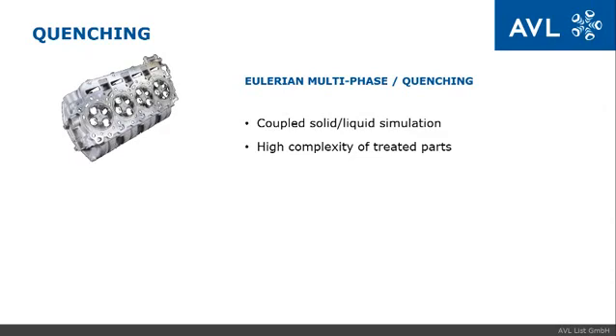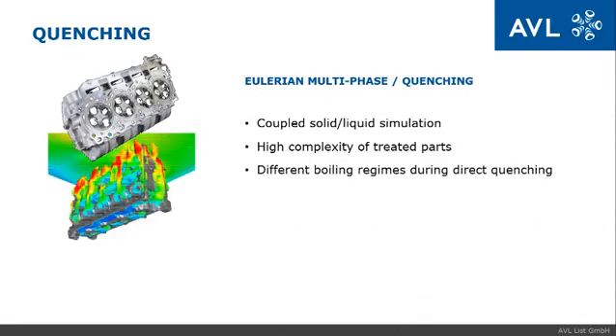We are talking about the treatment of highly complex components such as cylinder heads or engine blocks. The quenched component undergoes different boiling regimes — film boiling followed by transition into nucleate boiling — which are accurately captured by the utilized model.